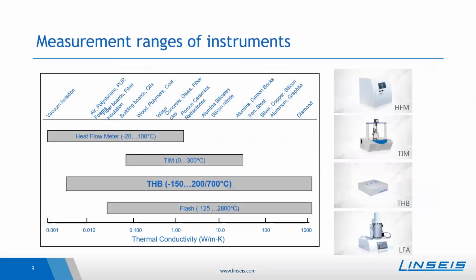This is also illustrated here on this slide, where you can see the thermal conductivity range here on the bottom, and here the different instruments. You see that the THB has more or less the broadest thermal conductivity range. The laser flash system has some difficulties for the very low thermal conductivities, but the THB is more limited in the temperature range. Because of that, the laser flash is still the most universal instrument. But with the THB also, a lot of different applications can be realized.